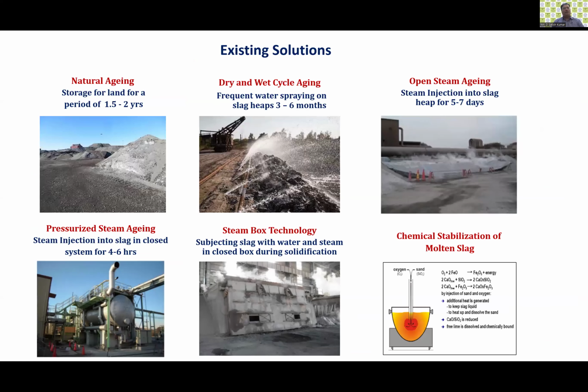Over a period of time, a lot of solutions have been developed to age these materials, starting from natural aging to dry and wet aging, to open steam aging, even pressurized steam aging and steam box technology. Even chemical stabilization of these slags has also been developed. These are technologies being developed in-house at many steel plants around the world. And these technologies make this slag conducive and matching to the specifications of the construction industry for aggregates. Now, these are additional steps being adopted and commissioned in many steel plants, including JSW Steel, where we are trying to convert this waste, avoid dumping, and convert it into products to be used.